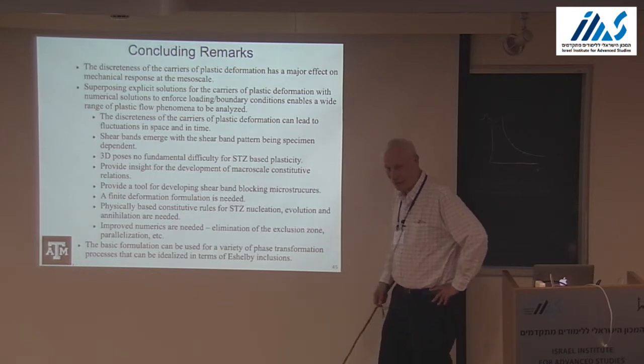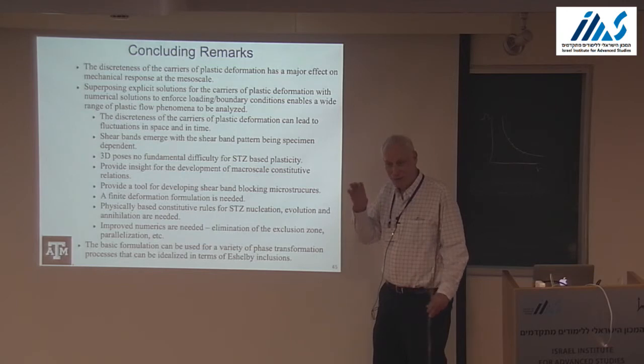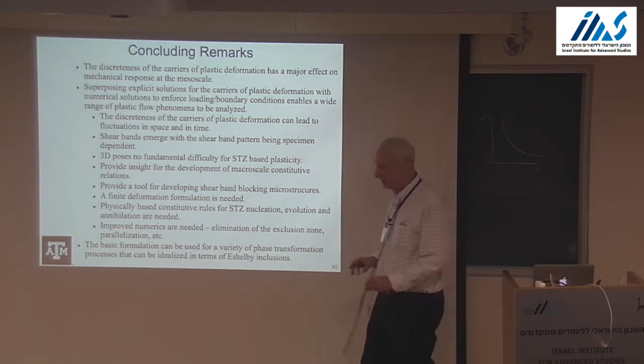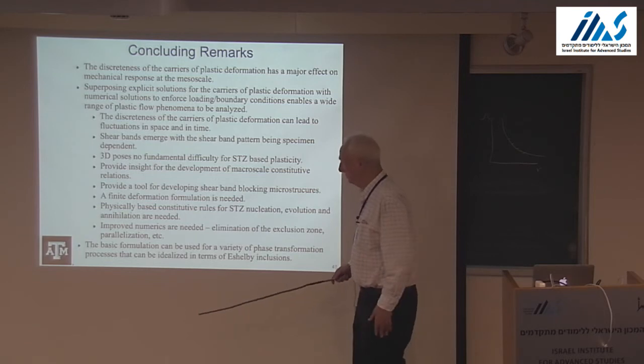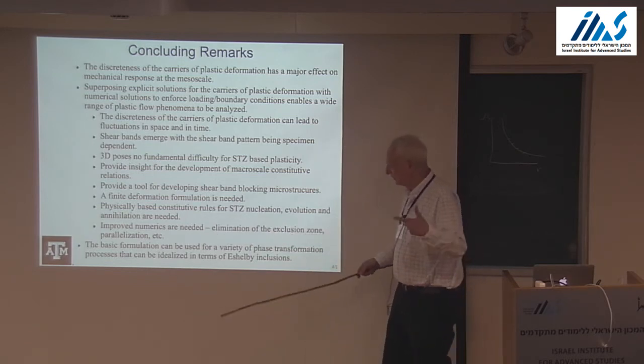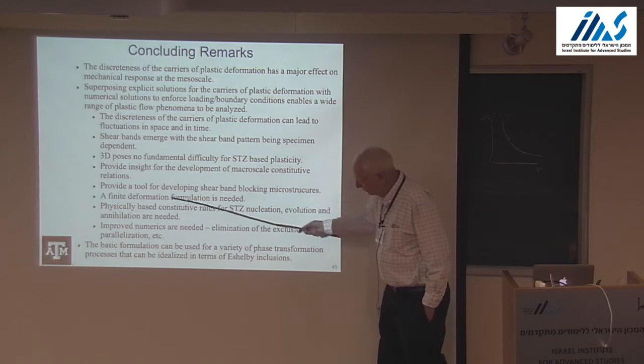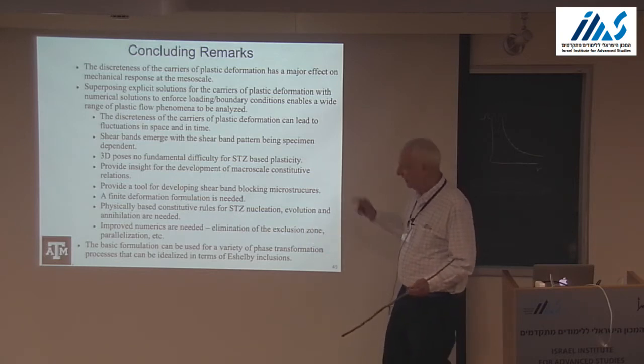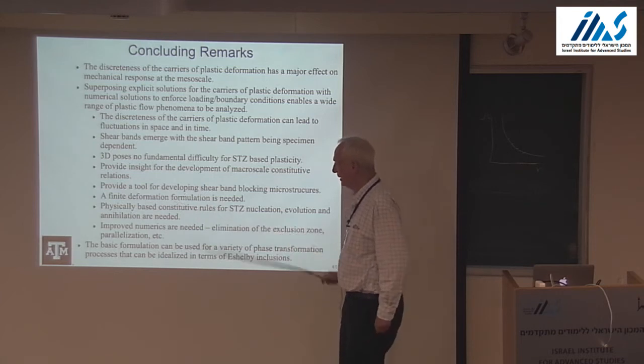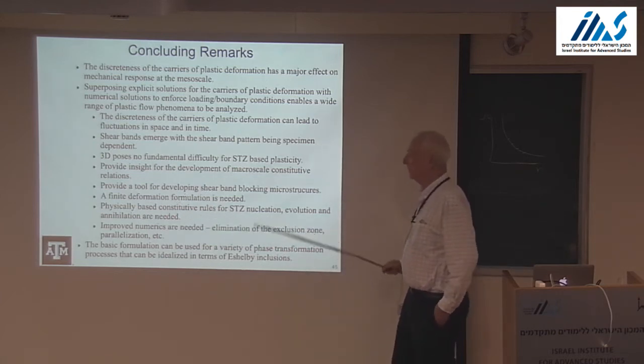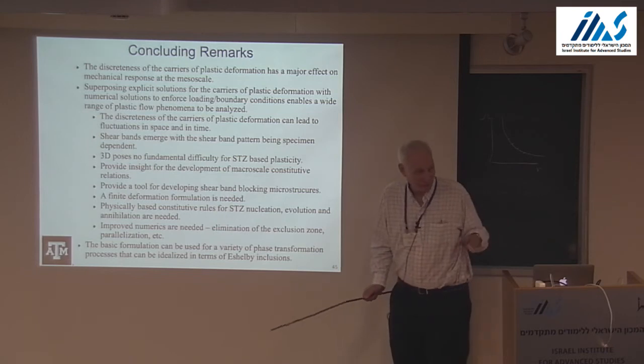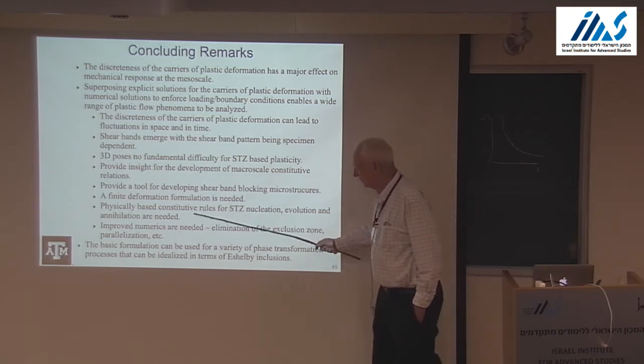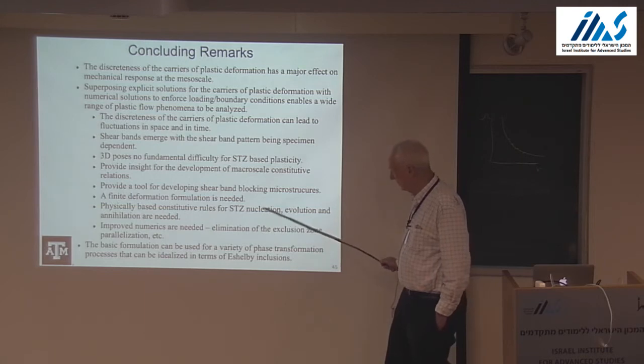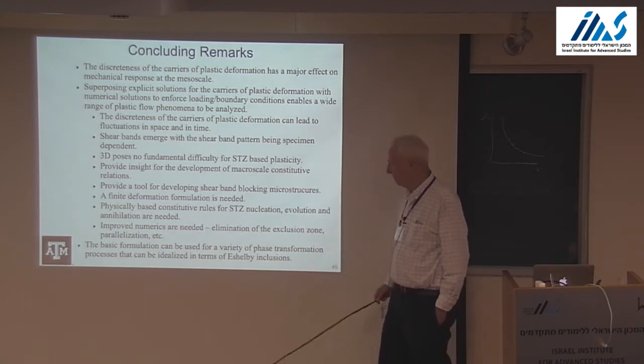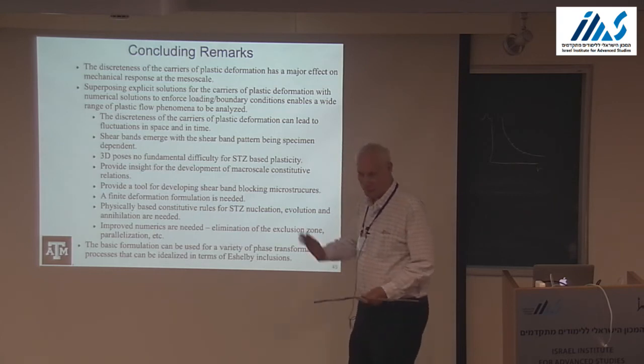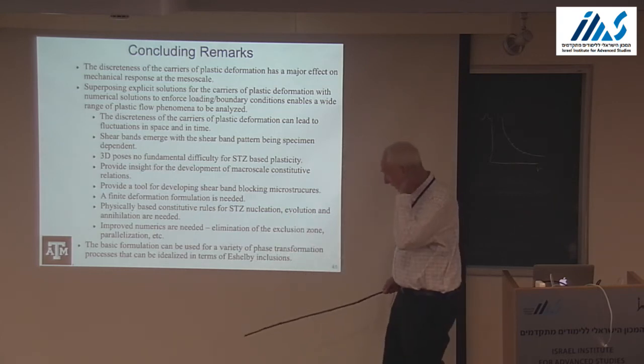shear band blocking microstructures. What happens if we put in a lot of holes? What about we put in some crystals, which we can do dislocation plasticity for? Inclusions, we can use this as a virtual tool. We need to account for finite geometry changes. That we know how to do for dislocations, we can port that here. This is the key thing we hope to get from people like Aaron and Michael and others: more physical-based rules for STZ nucleation, evolution, annihilation. And we can improve the numerics. We haven't parallelized the code yet, all kinds of things like that.